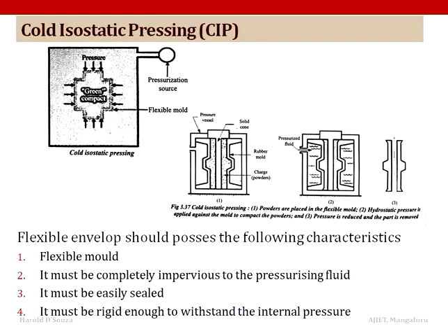Cold isostatic pressing. In this method, the powdered material is contained in a tightly sealed flexible mold which is subjected to uniform pressure around 65 to 650 megapascal, applied simultaneously from all sides, achieving uniform density and strength. After pressing, the compact is removed from the chamber. The pressure transmitting medium used is a liquid such as water or oil mixture.